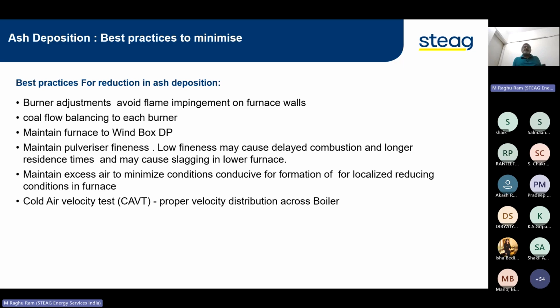How to minimize? The best practices: burner adjustments to avoid flame impingement, direct hitting on the furnace walls. It can be done by burner adjustments, coal flow balancing in each corner, maintaining furnace to windbox DP, which I was discussing earlier, and maintaining pulverized fineness. Low fineness may cause delayed combustion because particle size is more, it takes more time to burn, and longer residence times may cause slagging in the lower furnace. Maintain excess air to minimize conditions conducive to localized reducing conditions in the furnace. And a cold air velocity test can be done for proper velocity distribution across the boiler.